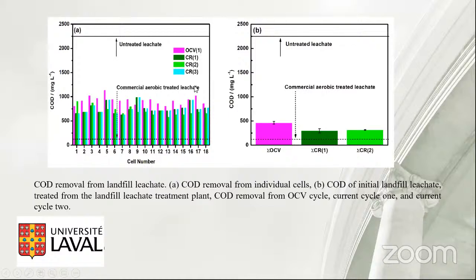And this is the commercial aerobic treatment leachate. So this is this line. Basically, the commercial plants can go up to this. And this is the overall scenario. When we consider the whole system, and we took samples from the whole system, you will see using the constant resistance mode, it was close to a commercial aerobic treatment plant. So wherever we got this sample, it was not that we couldn't reach that point, but we could reduce from 2200 to 250 milligram per liter.